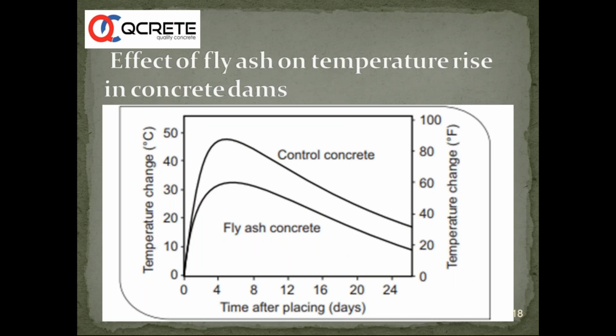One of the major effects when we are using fly ash in concrete is reduction in temperature. You can see in this graph that the fly ash concrete has a lower buildup of temperature, and control concrete has a higher temperature buildup, which can cause thermal stresses. So use of fly ash can help in mass concreting like raft foundations. Like the other SCM, GGBS, fly ash also has a significant benefit in terms of reduction of temperature, especially beneficial to thick structures like raft foundations.